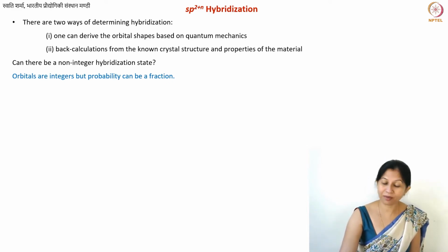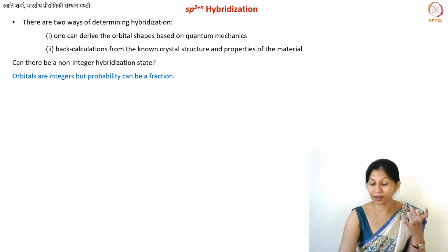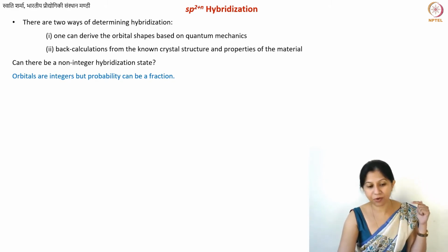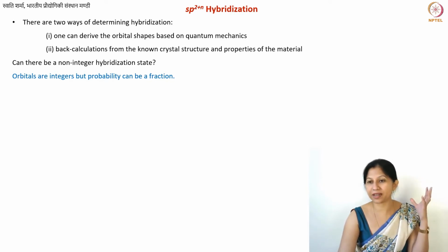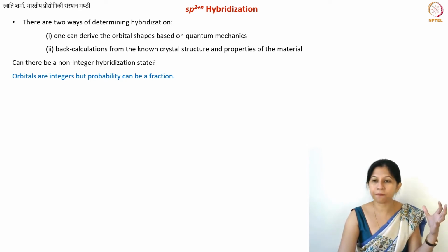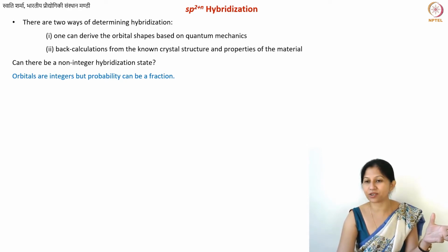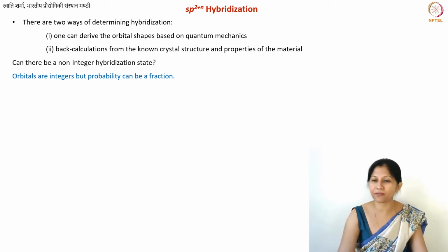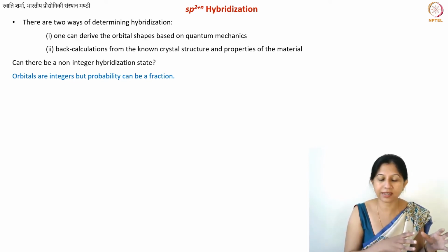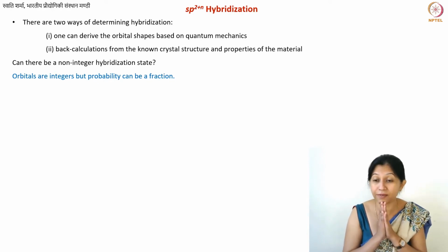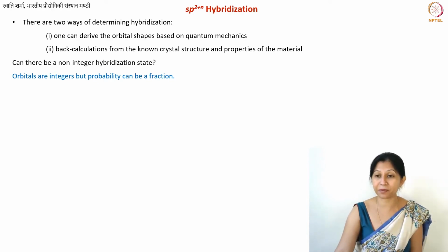So we talked about this unhybridized p orbital in the case of graphite. So we have 3 orbitals that get hybridized and they participate in bonding. In the case of diamond, all 4 orbitals get hybridized, and they form 4 molecular orbitals which are then filled. Basically, there is a bonding taking place. All of these electrons participate in bonding and they do not remain free afterwards. They are not really interested in doing anything else because they have already paired up. They have formed a bond. So these are sigma bonds, and then that is how we have the sp3 type geometries or sp3 type crystals.